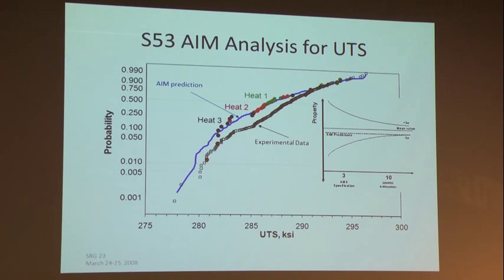In this case, in order to be a drop-in replacement, it was vitally important that we match this 280 KSI minimum number that allows us to replace the existing steel without any design changes of the components. In practice, at the level of 2 heats, these forecasts were able to show that we were at risk of not meeting that quantity. And so we were able to re-optimize the processing very early in the qualification program and save a lot of time and cost to meet that requirement.